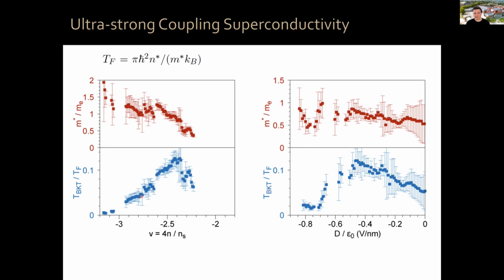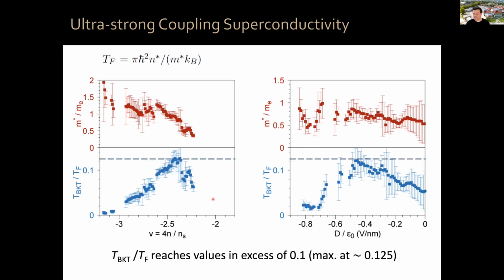And as you can see, TBKT over TF reaches a very large value. This is actually 0.125, okay? So TBKT over TF reaches values in excess of 0.1, with the maximum happening actually at about 0.125. Now, I don't want to make too big a story out of the fact that it coincides with 0.125.